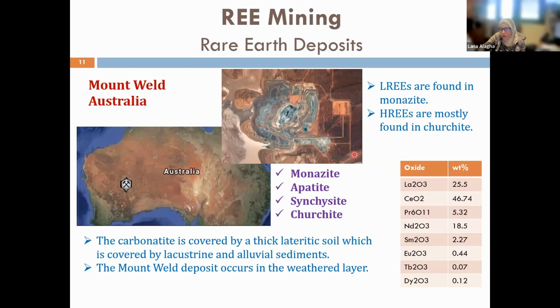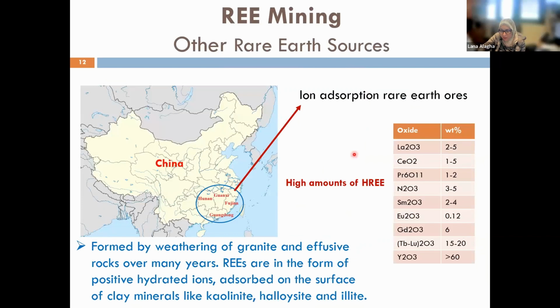Other sources of rare earth metals or elements are the ion adsorption clays. In this case, these are formed by weathering of granite and other rocks, and the REE usually adsorb on the surface of these clays, mainly kaolinite and illite. And you can see the average relative concentration of different rare earth oxides in these types of sources. It is mainly found in China.